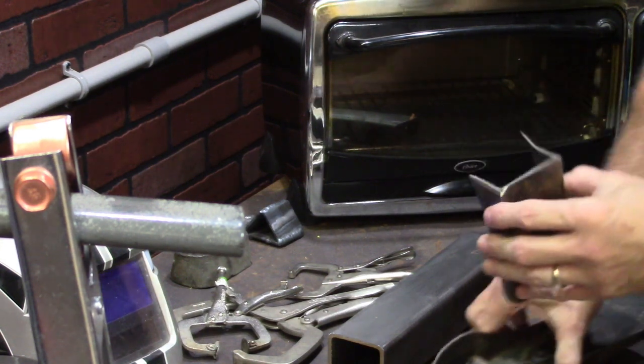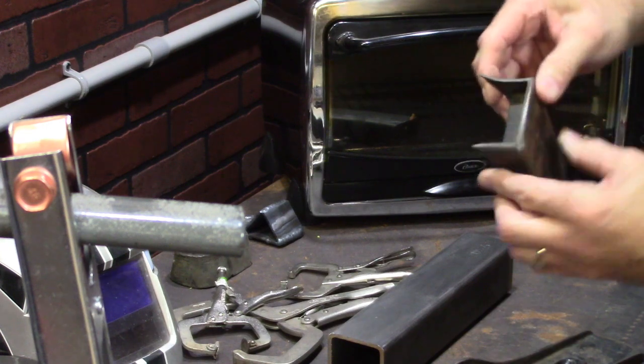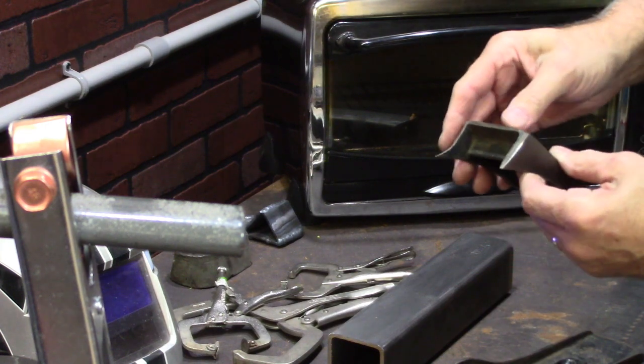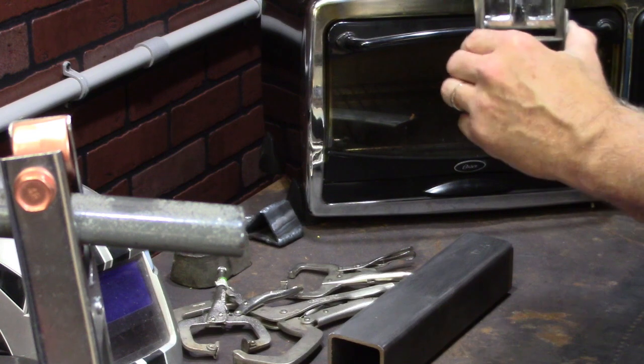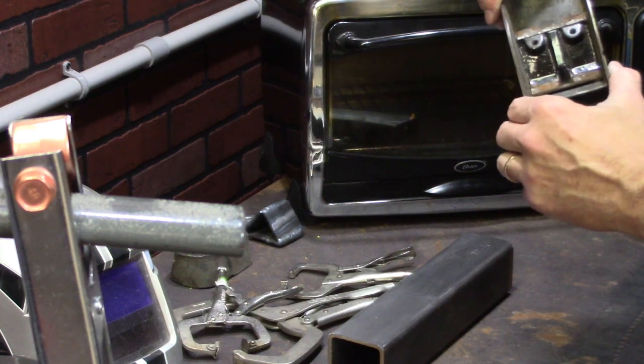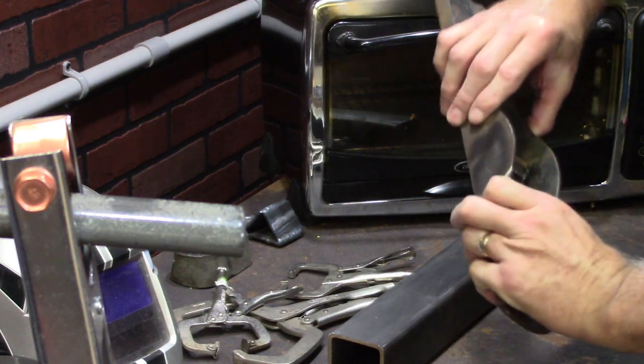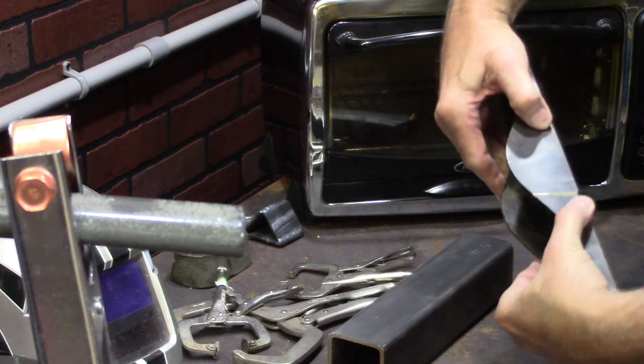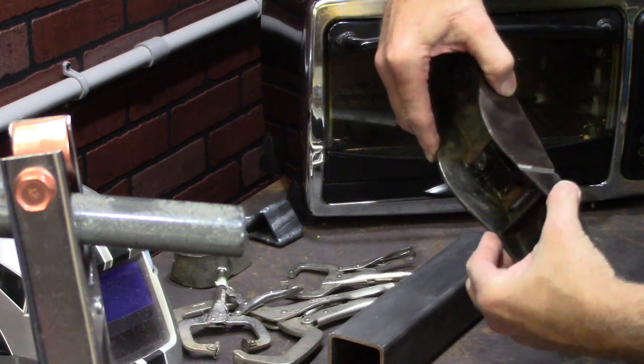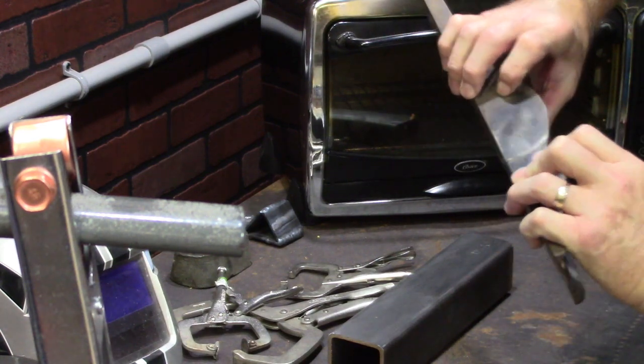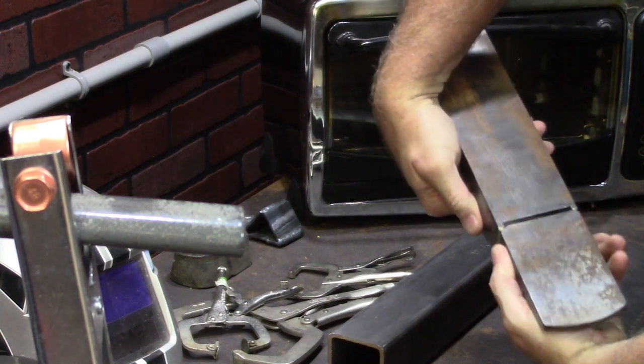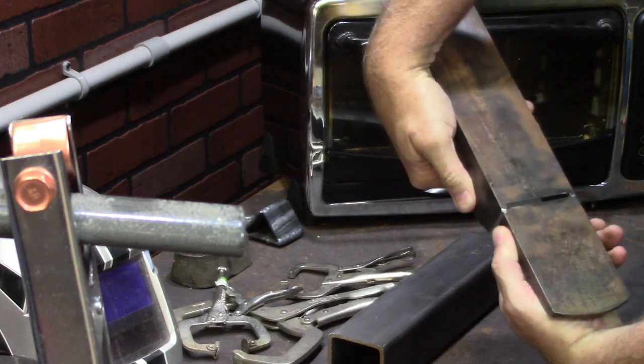Now I've also ground about maybe a 1/2 to 3/4 inch up on the web on the inside so that I can get a good tack on the inside of the web. The idea being is once I clamp this thing together, I can put 2 tacks in there, and then I can pull the clamp out of there and work on the thing without too much trouble.